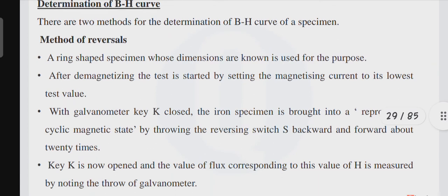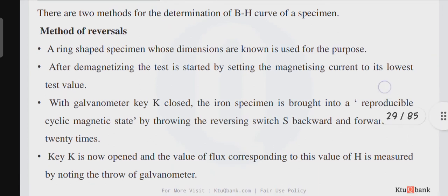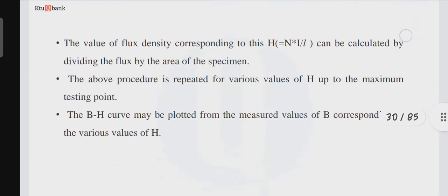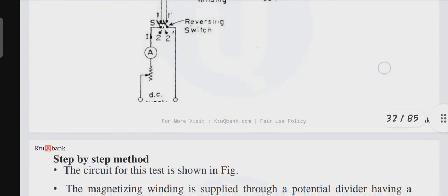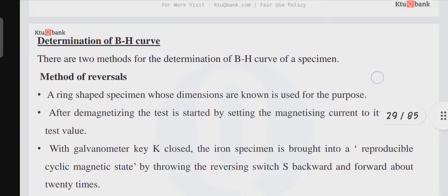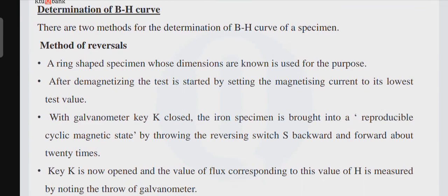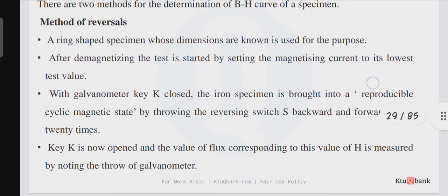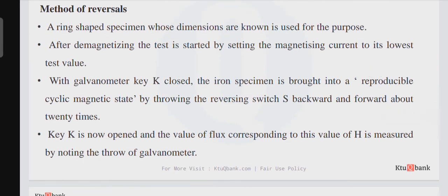Determination of BH curve. There are two methods: method of reversal and step-by-step method. Method of reversal. A ring-shaped specimen whose dimensions are known is used for the purpose. After demagnetizing, the test is started by setting the magnetizing current to its lowest test value. With galvanometer key K closed, the iron specimen is brought to a reproducible cyclic magnetic state by throwing the reversing switch S backward and forward about 20 times.